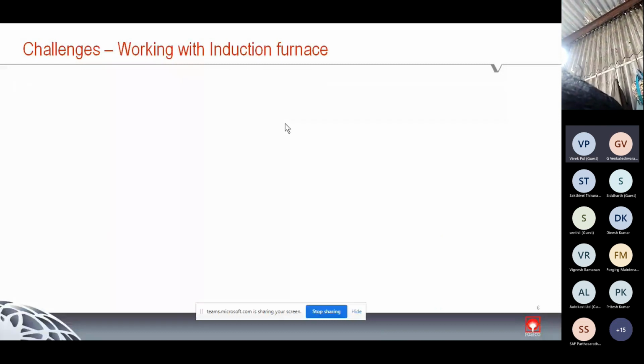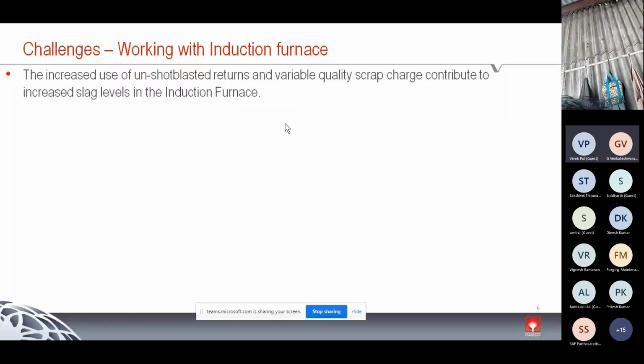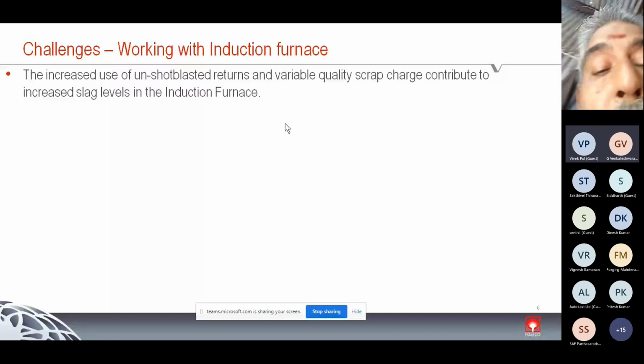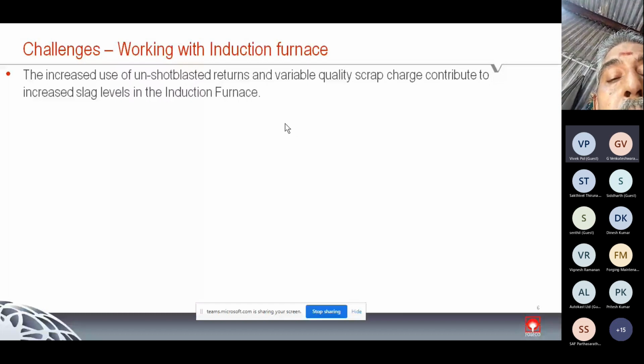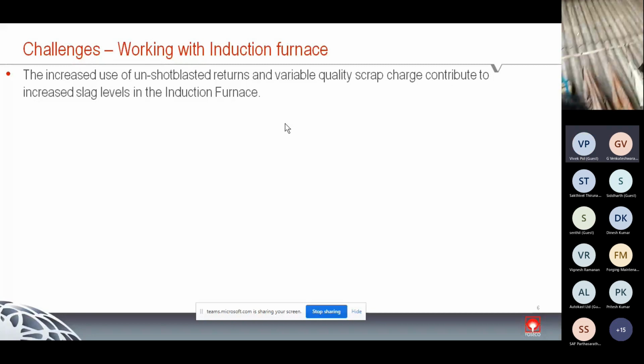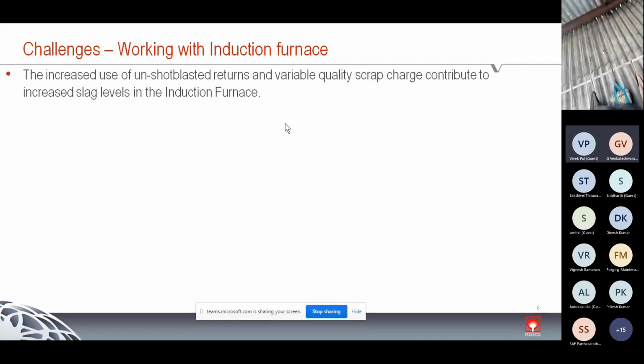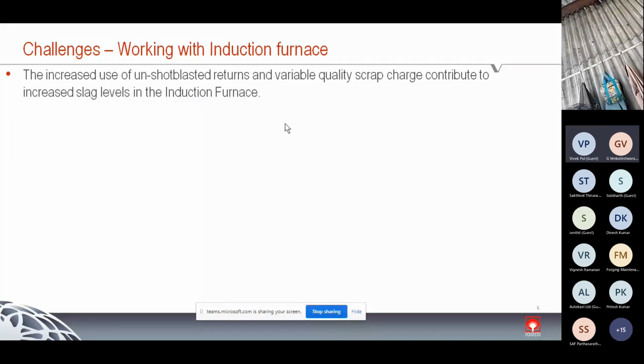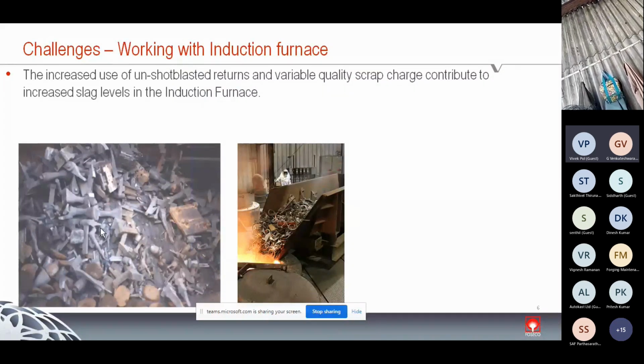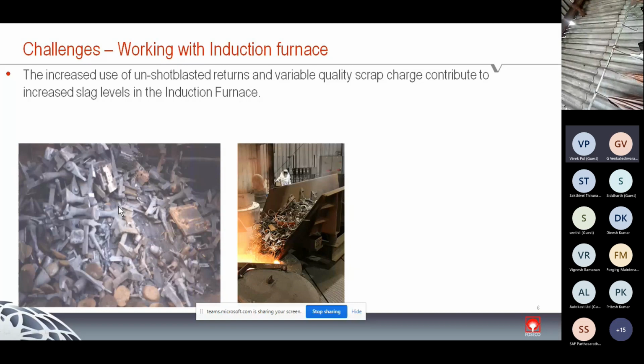Though the benefits are very good, there are some challenges that every foundryman comes across while working with induction furnaces. For example, the increased use of unshot blasted returns and variable quality scrap. On one side it is a benefit, but the use of excessive borings and unshot blasted returns could lead to an increase in slag levels, and that is one of the major challenges. You can see unshot blasted returns have a lot of sand, which is used during charging, and that would lead to slag generation.